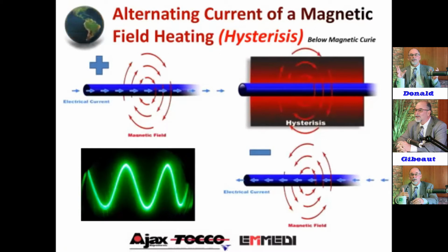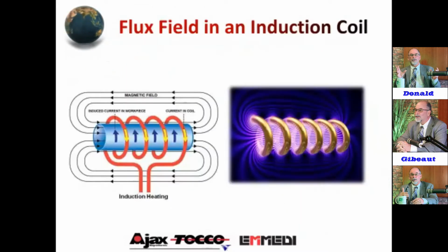So, typical frequencies here for tube heat treating is anywhere from 600 hertz, that's 600 pulses per second, up to probably 10 kilohertz, which is 10,000 of these cycles per second. Now, when we get up into the high frequency HFI welders, we're up to 500 kilohertz. That's 500,000 cycles a second. So semiconductors play a big part in this technology, but very precise. Again, this is the flux mapping we talked about with the picture to the right, and the one to the left actually shows the workpiece, the tube, inserted in, and how the magnetic field passes through the tube.